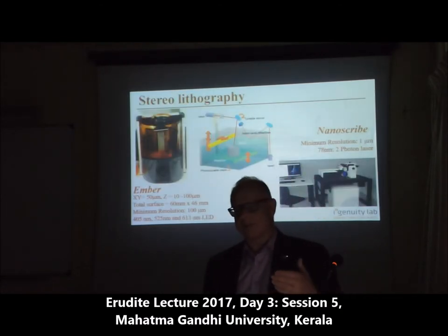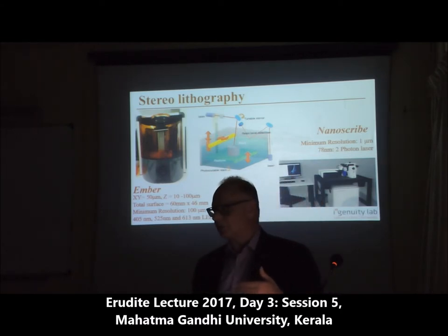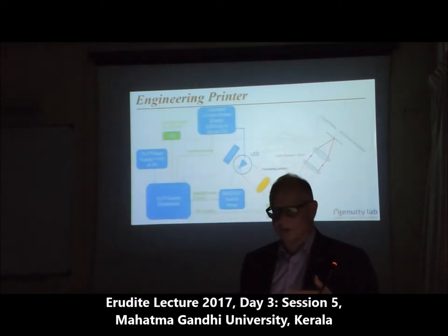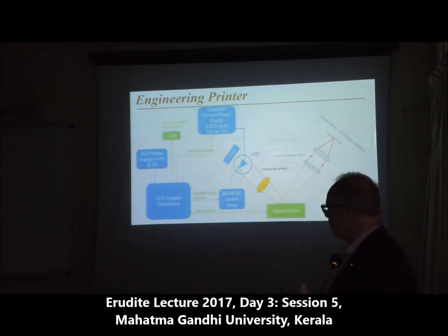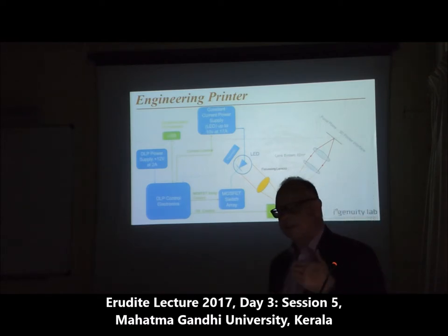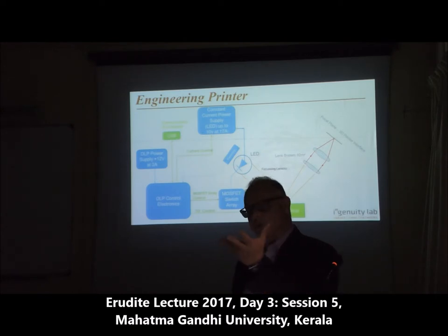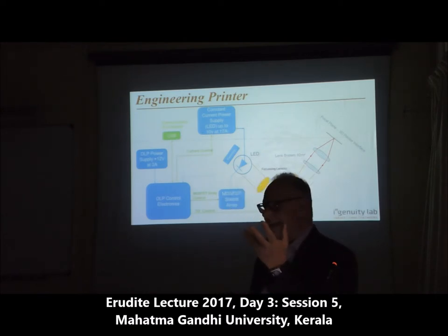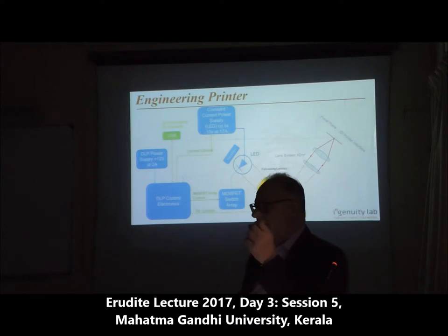To do this, we're making machines that use stereolithography. I'm having the second prototype of the machine built here in Kochi. We have a controlled light source that puts out different colors of light, using a DLP chip like you'd find on advanced projectors. We project an image of different colors of light to enable the polymerization of only those polymers that polymerize at that color of light in that position.